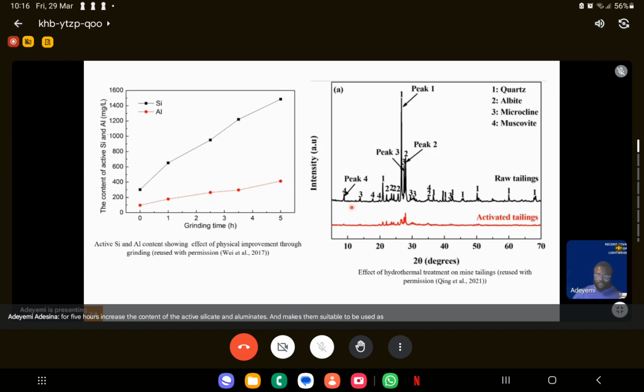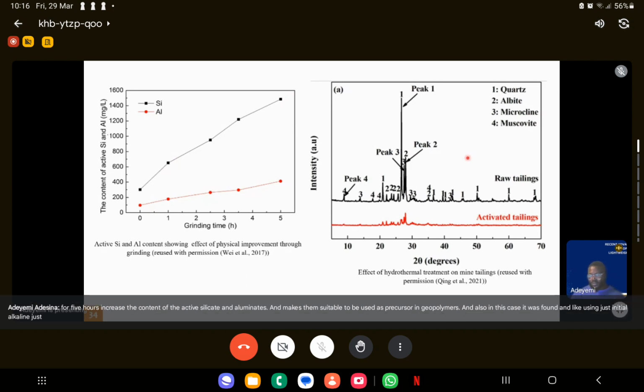And these are just some of the results from the activation method. In this case, they found that if you have a mine tailing, just grinding it alone for 5 hours increases the content of the active silicate and aluminates and makes them suitable to be used as precursors in geopolymers. And also, it was found that using just initial alkali to cover the precursors resulted in the deterioration of all these peaks, which means in this case we have more amorphous phase compared to this one. So this treatment could be done with minimal energy. It's not energy intensive. And at the end of the day, because we're replacing cement totally, this is still very sustainable.